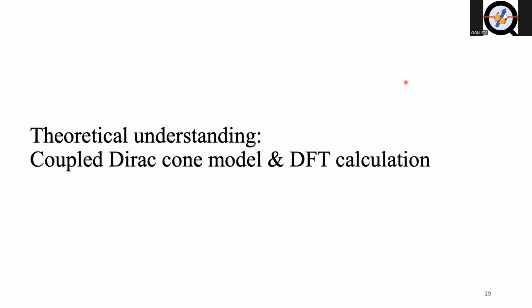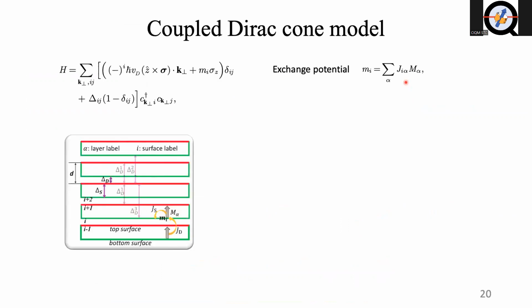So next would be, how are we going to understand this suppressed Dirac mass gap caused by those defects? To do that, we performed a coupled Dirac model together with DFT calculation. Let me introduce the coupled Dirac model first. The coupled Dirac model considers the Dirac cones that live on the top and bottom surfaces of each quintuple layer, and we allow coupling for those Dirac cones within the same quintuple layer, as represented by this delta S, or with adjacent quintuple layers across the van der Waals gap, as represented by this delta D. Here I and J denote the quintuple layers, and M is the exchange potential, which can be written as such.